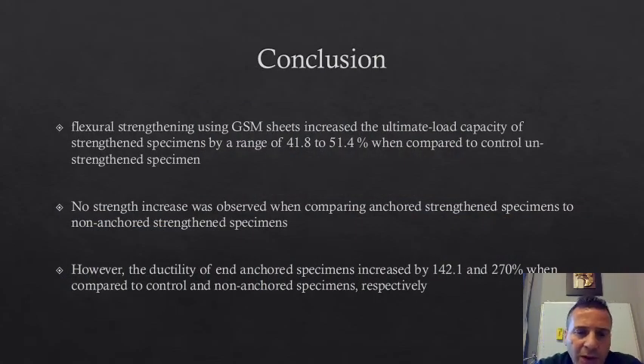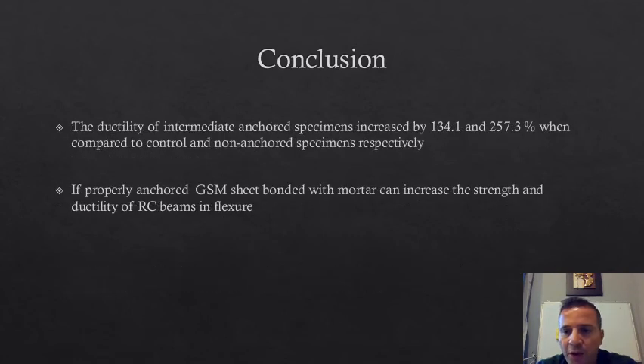So in conclusion, using GSM sheets can increase the strength of reinforced concrete beams in flexure up to about 50%. If you don't anchor the ends, the ductility will decrease. This is common: as you increase the strength, the ductility decreases. However, if you put end anchors, your wraps at the ends, your ductility will increase by up to 270%, which is very good. And it can reach up to 257% over the control and unanchored specimens.